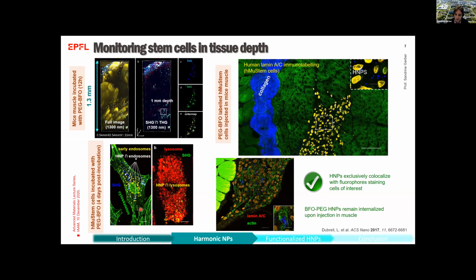As you can see, ex vivo analysis of this tissue showed, here and also in this second image, that the nanoparticles, shown as blue spots, exclusively colocalized with the fluorescent staining of the cells of interest, the ones that were injected. You clearly see the nanoparticles are not present in other areas of those tissues, so you can really track those cells thanks to the presence of this harmonic nanoparticle over a long time.